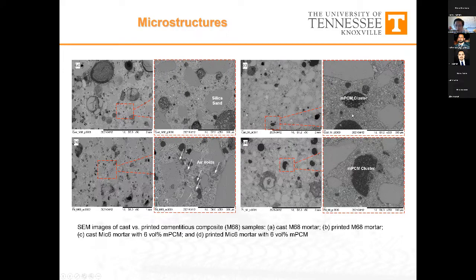As you see, it's a little bit porous. Those are actually PCM capsules. Because of this lubricating effect, I think to a large extent it has helped to eliminate some of the large air voids inside the printed sample, as we can see in its microstructure.